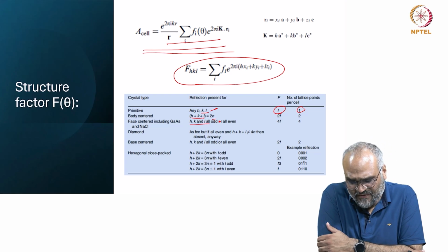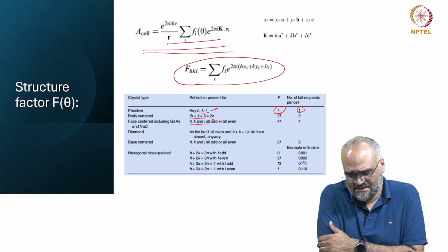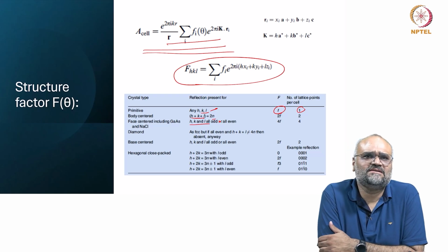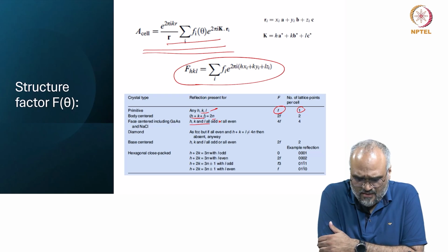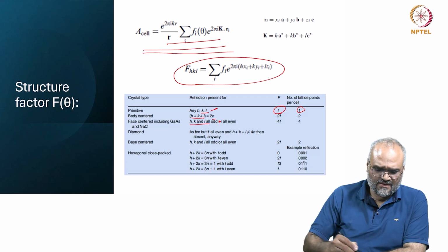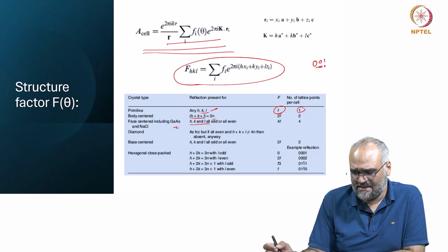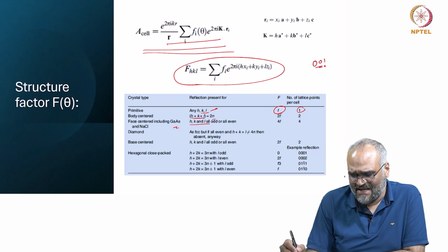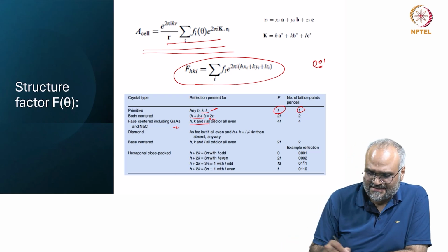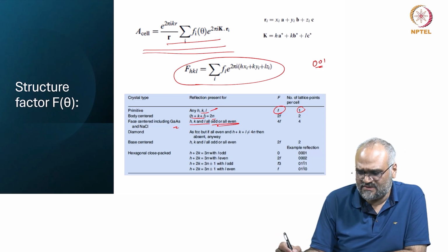Now, what is different between the regular X-ray diffraction patterns and the electron diffraction patterns is that, sometimes depending on the orientation of the crystal that you are looking at, not all reflections might actually be visible. As an example, I can take the case of a face-centered cubic structure. Let us say I am orienting my face-centered cubic crystal in the 001 zone axis. In this situation, for the reflections I see by using the Weiss zone law, there is a possibility that the HKLs for all the values satisfying the condition of all being odd or even should give me a reflection.